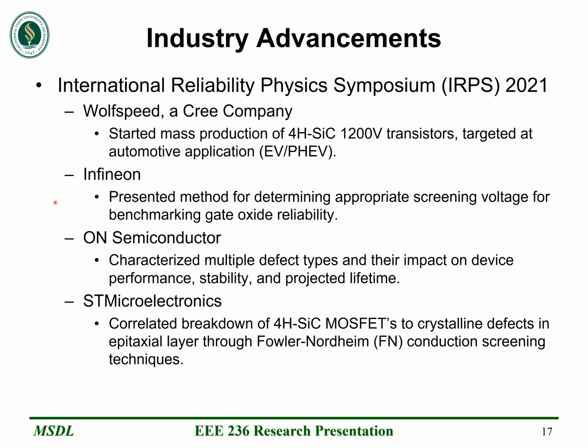Infineon presented a method for determining the appropriate screening voltage for benchmarking gate oxide reliability. On Semiconductor characterized multiple defect types and their impact on device performance, stability, and projected lifetime. And lastly, STMicroelectronics correlated the breakdown of 4H silicon carbide MOSFETs to specific crystalline defects in the epitaxial layer using Fowler-Nordheim conduction screening techniques.